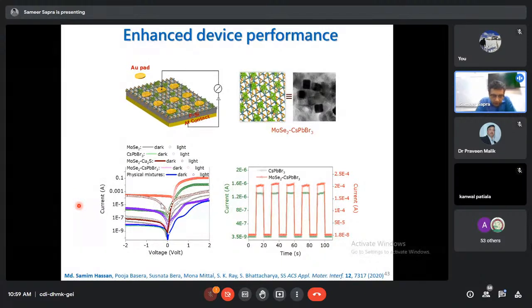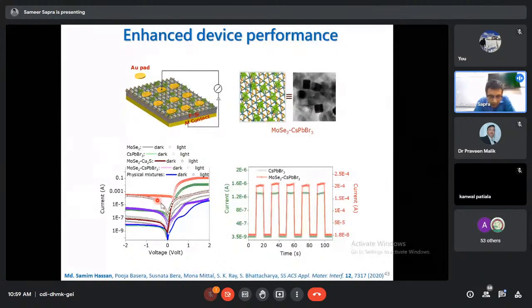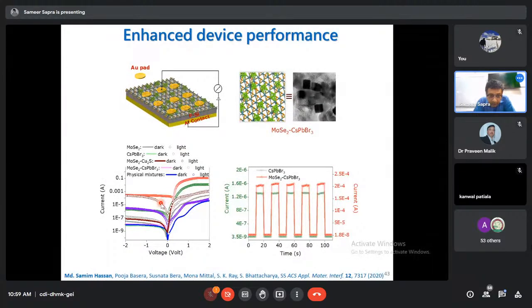This is, the brown open dots are molybdenum selenide, cuprous sulfide. Yes, the pointer is sitting right on top of it right now. And the one above it, the red one, is molybdenum selenide, cesium lead bromide. Okay. Not much difference in the light currents, but the dark currents in cesium lead bromide are much lower. And this is about 5 orders of magnitude difference, whereas in the cuprous sulfide, we had about 3 orders of magnitude. But the good thing, 3 to 4 orders of magnitude, okay.